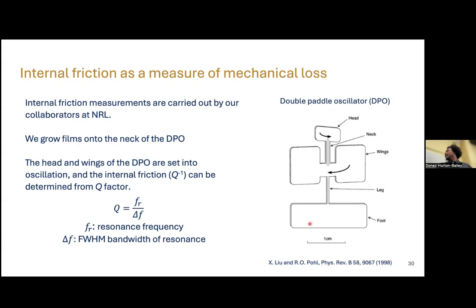And what they do is they clamp down the foot, and they set the wings and the head of the DPO to oscillate in an anti-symmetric oscillation. And this causes the film to twist. And basically setting this as a ring down, think of a damped harmonic oscillator, it'll dampen over time, and we're able to measure the quality factor Q, and the internal friction is the reciprocal of that value. So Q inverse is the internal friction that I'm interested in seeing.